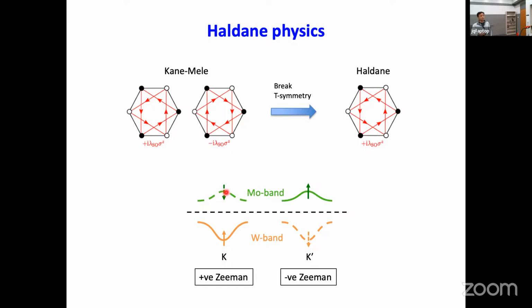You can see that for the Mo-band, the K valley is spin down, and the K prime valley is spin up. But for the tungsten, it's totally opposite because of the A-B stacking. We rotate by 180 degrees, right? So for the tungsten, it's spin up for the K and spin down for the K prime. And what that means is that once we apply a magnetic field to the system, the K valley will get a positive Zeeman effect, so the gap would enlarge. And then the K prime valley would develop a negative Zeeman effect, and the gap would shrink, okay?